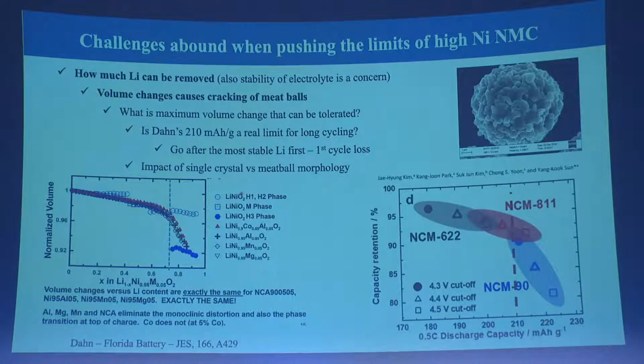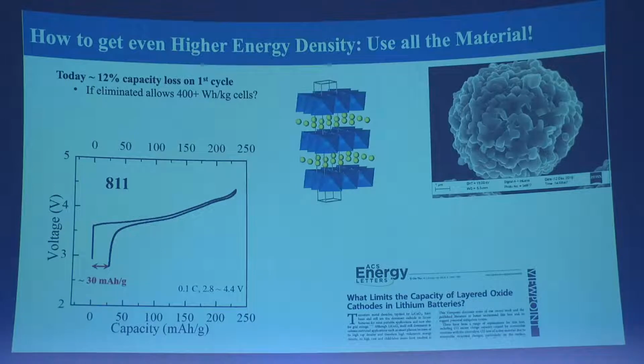So Jeff Dahn and the Koreans did some studies on these materials, and Jeff Dahn found out the lattice volume didn't change very much until you took out more than 70% of the lithium. And you can see how it falls off the cliff on the left-hand side over here. That's where the cracking starts. And he says if you go above that limit, you're not going to get long cycle life. The Koreans did similar studies. They looked at capacity loss, and you can see the same plot. As soon as we go to high nickel, we push it to high capacity, then we have capacity loss. So our goal is to say, can we eliminate this? Can we go to high capacity and not have this capacity loss? And what we ideally would like to do is use all the lithium in the material so we don't have to stress them so much. But I'll come back to these meatballs in a moment.